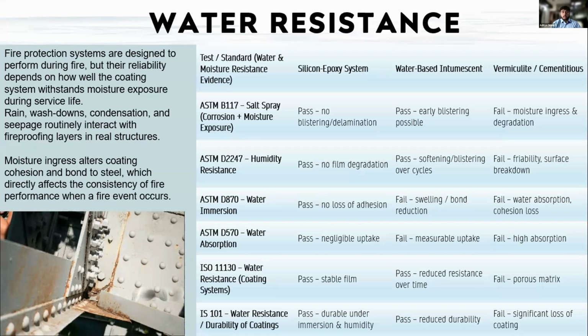Water resistance is also a really crucial factor when you are going for fireproofing on a steel substrate, where test standards are made according to ASTM B117. That's a salt spray test where corrosion or moisture exposure is studied. Silicone epoxy passes that test. Water-based also passes that test, but vermiculite coating fails that test due to moisture ingress and its porous nature, allowing the water to enter.